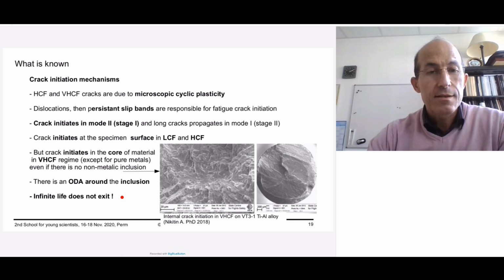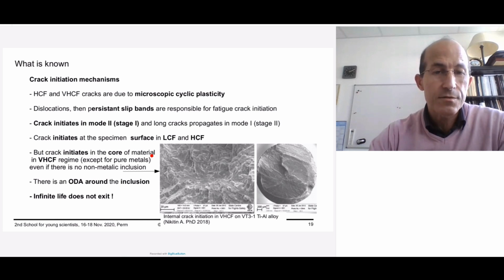Another important thing that is well known is that on metallic alloys, the crack initiation is mainly governed by the surface of the material in high cycle fatigue and low cycle fatigue. But when the number of cycles to failure increases up to 10 to the 8 or 10 to the 9 cycles and more, in the very high cycle fatigue regime, the crack initiation shifts from the surface to the core of the material, and the non-metallic inclusions are responsible for this crack initiation in the core of the material.